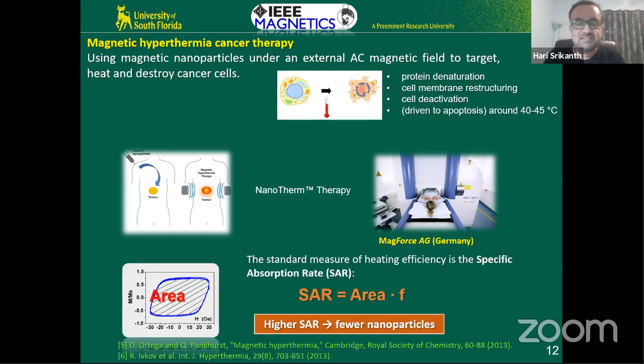So what is the physics behind this? The physics is very simple. We need to have a large hysteresis, okay? Now, those of you that are working on magnetic nanoparticles know that superparamagnetism means there is no hysteresis, right? You remove a field, it just comes back to zero because of the particle size being very small. The hysteresis we're talking about here is not the DC hysteresis, but it's the AC hysteresis. So the physics is very different. The process is very different. So you know that if you have a hysteresis curve like this, the area inside the hysteresis curve is dissipation, and dissipation here is in the form of heat. And that's how we generate local heat to kill, to fry the nanoparticles, okay?